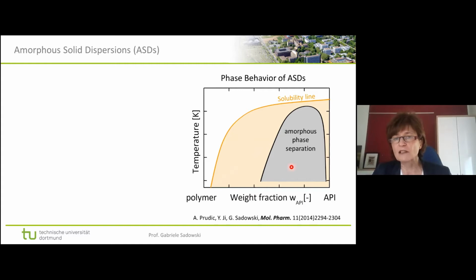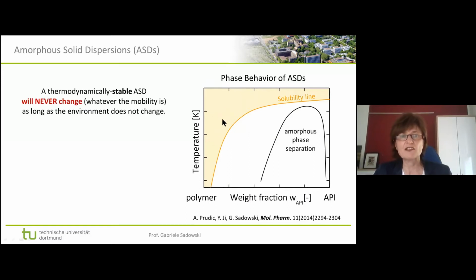And of course, in this particular case, this demixing region is completely below the solubility line. That means once you would be here, you would get phase separation. And after a while, you would also get crystals. And this is again what you don't want to have. So being in the orange or in the gray area means we do not want to be there. This is the unsafe region. So the best thing is simply to stay outside. So this is really the safe region, where for all the composition-temperature points we could go here, we would have a thermodynamically stable ASD. And that means once we are there, those ASDs would never change during storage, for example.